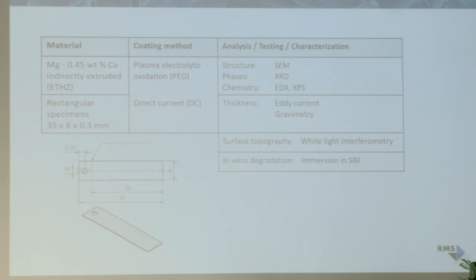Next example, research we did recently in collaboration with ETH Zurich. Here we had a new alloy which was developed in recent years, which contains only high-purity magnesium with a little bit of calcium. We used a rectangular specimen and coated it with the PEO coating, and did a number of characterization tests, which I'm going to show you.